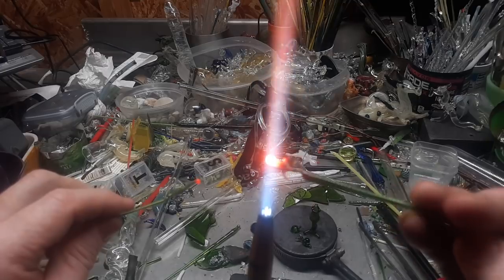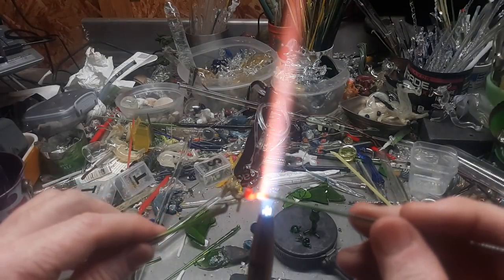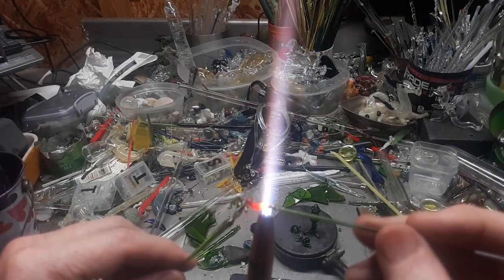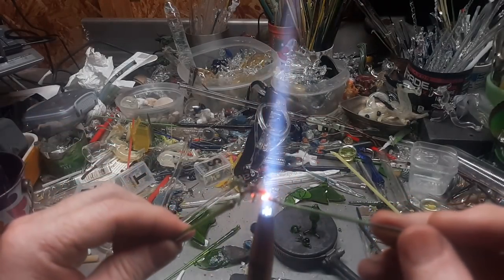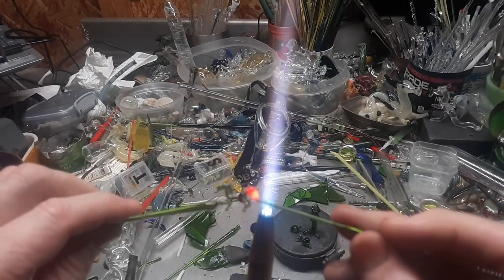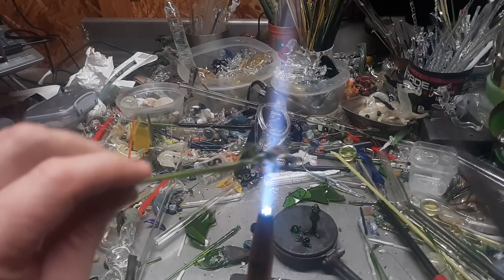Practice, practice, practice and more practice. Even small things — with soft glass, the smaller you make it, the more chance it will survive without putting it through the oven. I'm not saying something like this can't break and shatter without the oven, but the smaller it is the better chance of it surviving. Having an oven, or at least a fiber light or a crock pot to stick it in, would help. Things I didn't know then that I know now.